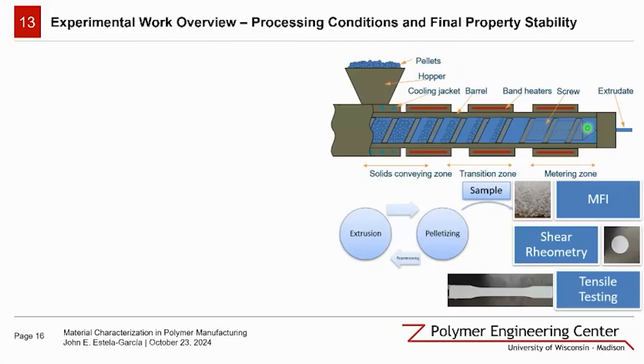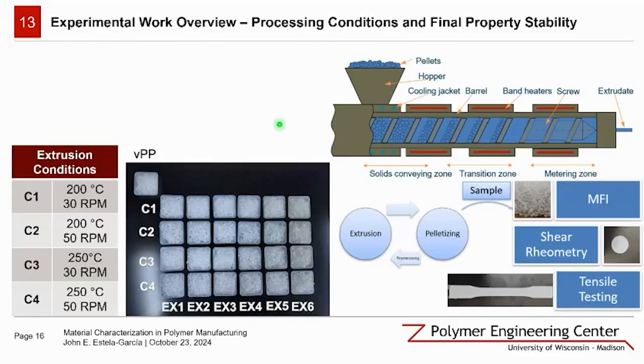So here we have an experimental setup that's mimicking real world conditions. We are pushing polypropylene through multiple extrusion events, mimicking PIR. This approach allows us to see how the material changes over time, giving us insights into the longevity and recyclability of the polymer. So we use different processing conditions where we can gauge the impact of specific variables on the stability of the material's properties. Each pass through the extruder leaves its mark, and we can see this unfold right here in this image, where we can appreciate the changing appearance of our samples as they are continuously exposed to the same extrusion conditions over and over again.